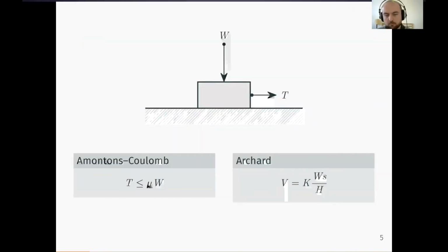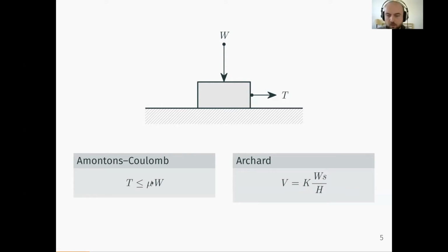However, there are no predictive models for either friction or wear. Here I selected two rather simple models for friction and wear. You have the familiar Amontons-Coulomb friction law with the friction coefficient, and a simple wear law, which is the Archard wear law, which states, if you're not familiar with it, that the wear volume is proportional to the normal force times the sliding distance divided by the hardness of the materials in contact. What both of those models have in common is that they need a coefficient: K is called the wear coefficient, and mu is the friction coefficient. Those coefficients need to be informed with experimental measures, and therefore, those models are not predictive.